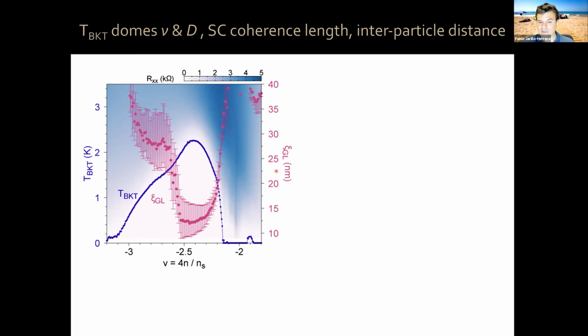We can compare the Ginzburg-Landau coherence length, which tells you roughly the Cooper pair size, with the average interparticle distance in our system. Remember, these Moire systems are extremely dilute because the superlattice unit cell is 100 times larger than atomic lattices. As you can see, the superconducting coherence length at optimal doping is of the same order as the interparticle distance. So Cooper pairs are as big as the average interparticle distance, okay?